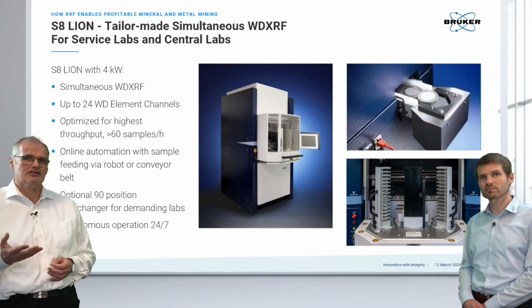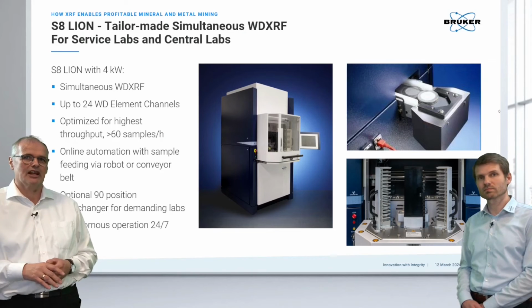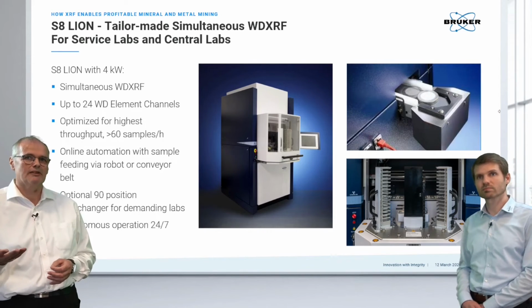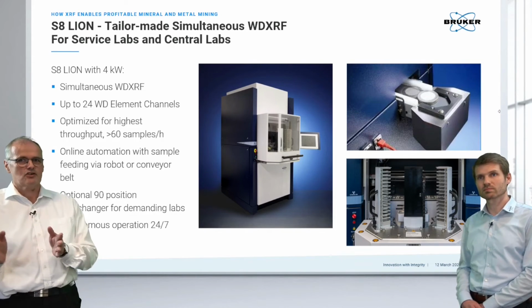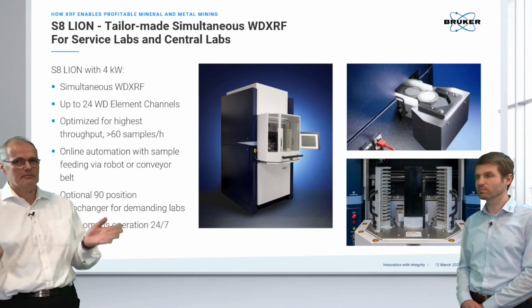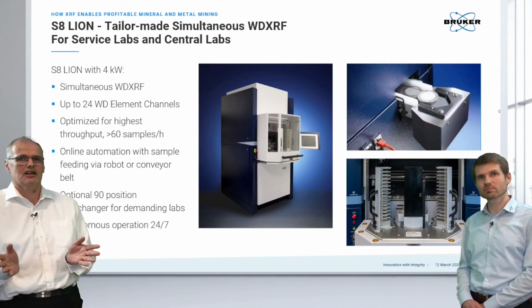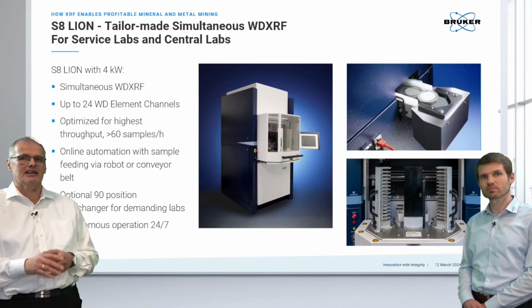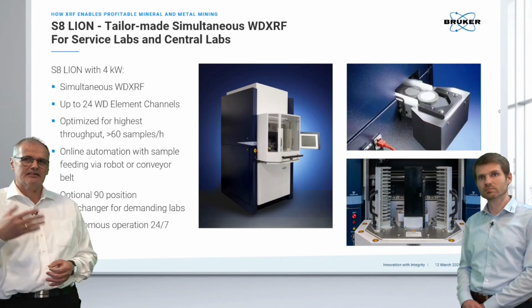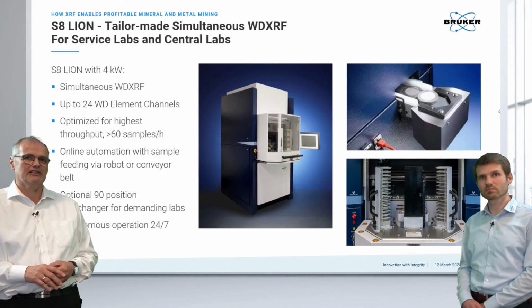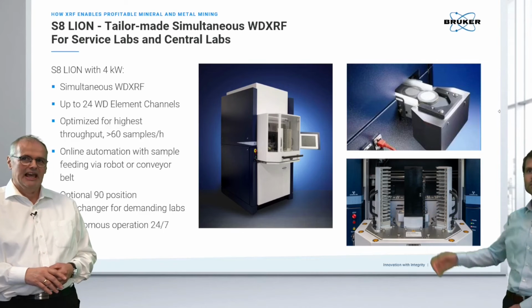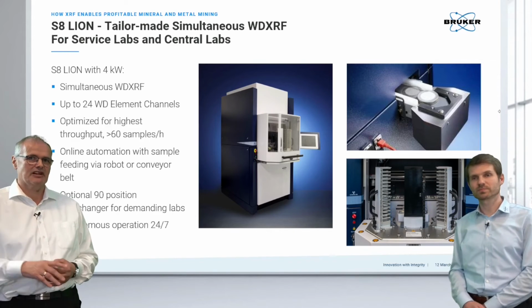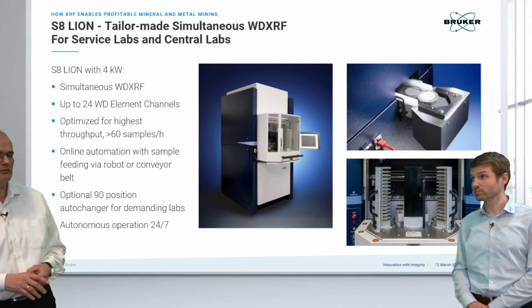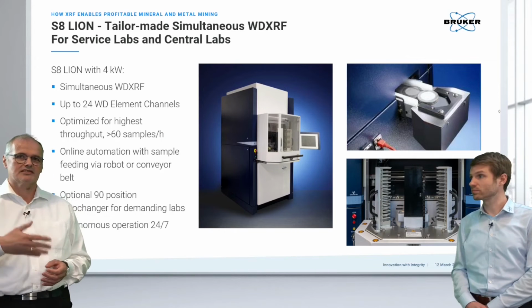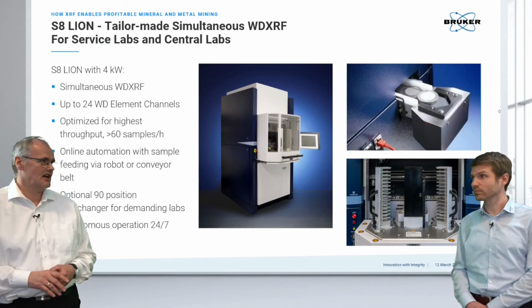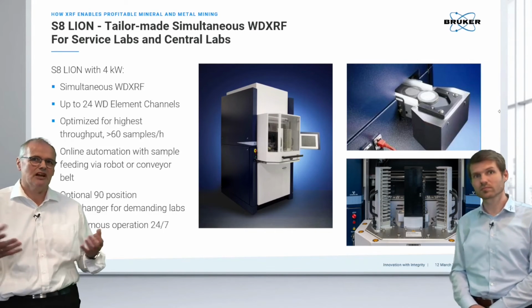For some applications like the service labs or central labs, we have a so-called simultaneous wavelength-dispersive unit. This is configured to cover the element range for a particular application. And each element has a dedicated channel. Equipped with an auto changer of 90 samples, we have typical measurement times of less than 1 minute per sample, which means that we can process more than 60 samples per hour, which is kind of Formula 1 speed.